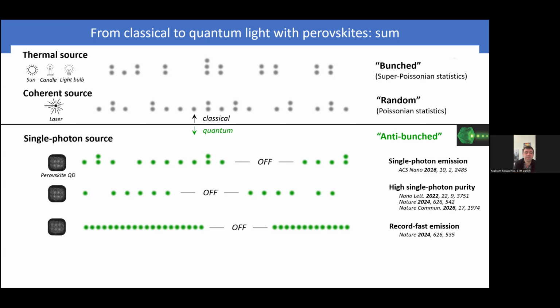And there are other groups reporting continuous layers or such quasi-epitaxial quantum dots by just thermal evaporation, or by more like a chemical vapor deposition, when you have a lead bromide and cesium bromide source, and then they find each other on a substrate. And that's sometimes very practical as well, I believe.